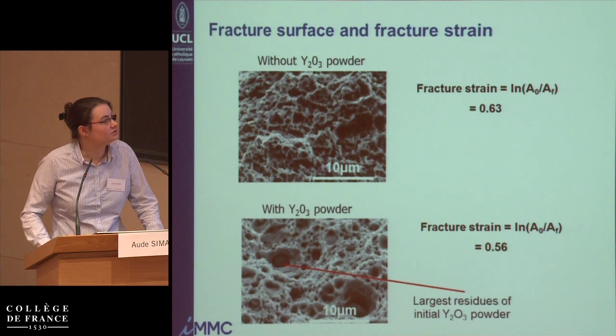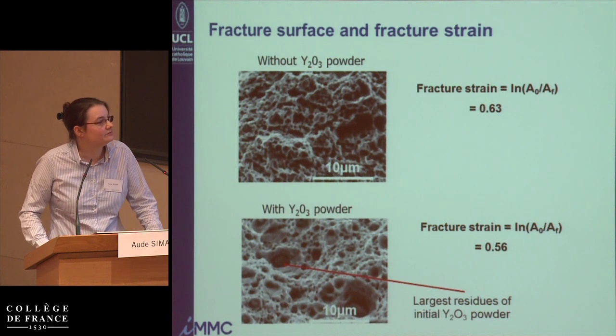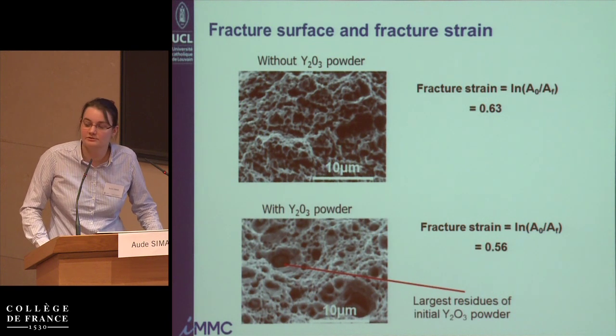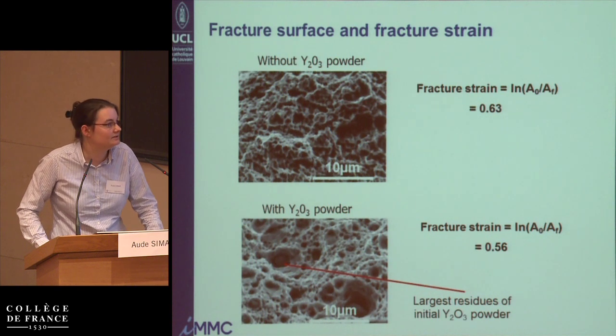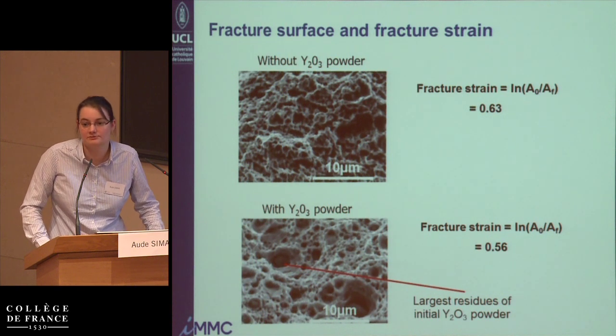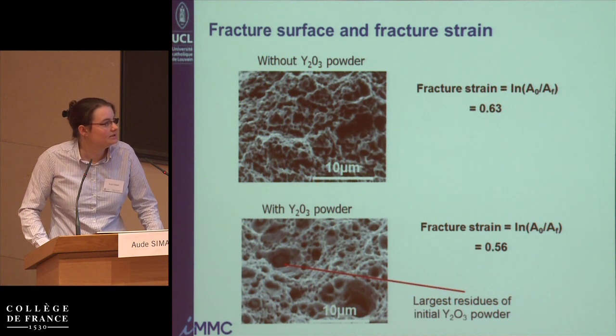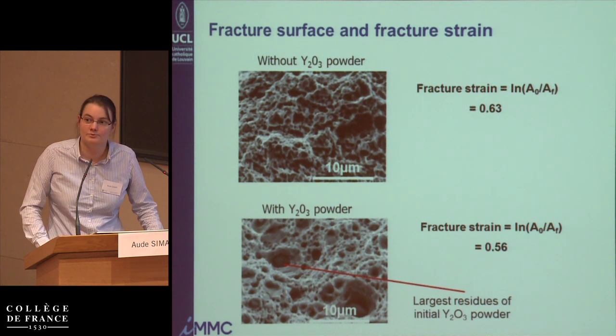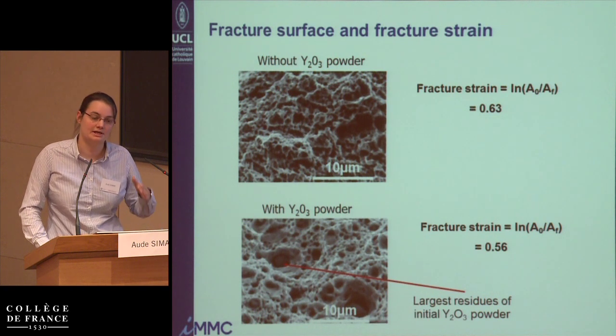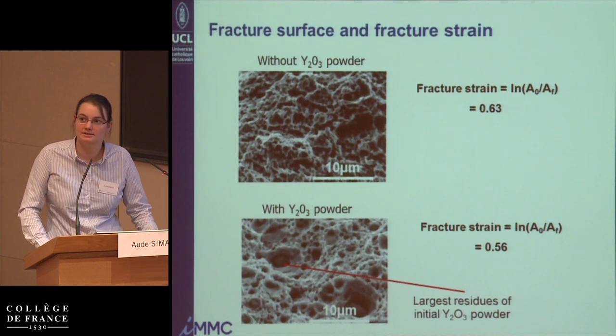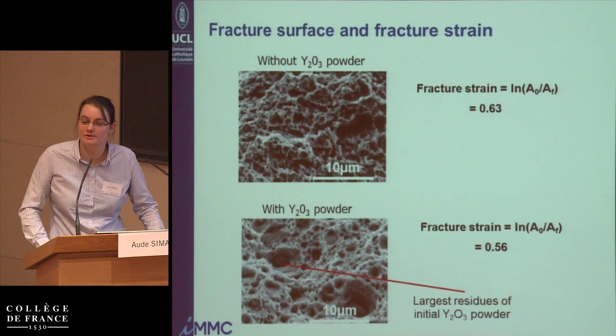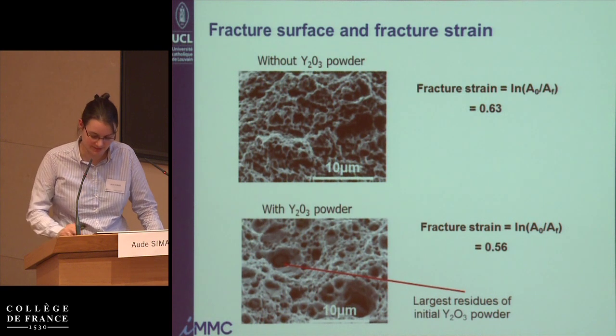And here, this is just to show you that fracture, of course, it was not a very ductile material, and that fracture occurs on the large particles. So if we can take out the large particles, well, then, of course, we can improve the properties of that material. So if we can only have very small particles and not the larger ones, well, we'll improve the ductility of the material.